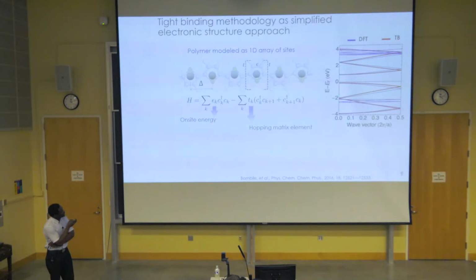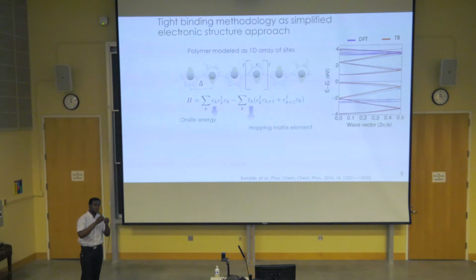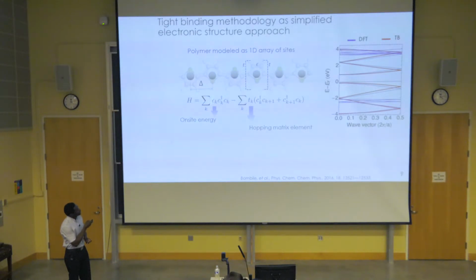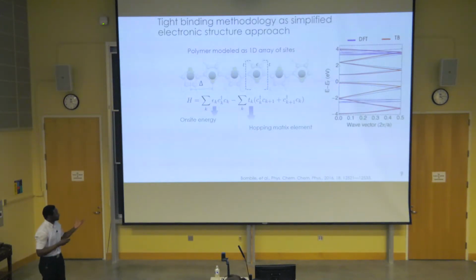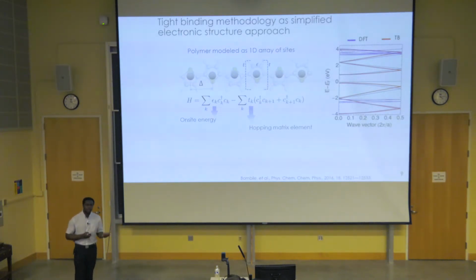And the energy of a charge carrier within this array can be captured by this tight binding Hamiltonian, where the first term here represents the energy of a charge carrier sitting on a single site. And the second term here captures how much the energy of the system is lowered when the charge carrier is able to spread out to the nearby site by quantum mechanical hopping. You don't need to know the details of the equation, but these are the creation and annihilation operators. But this equation has two parameters, the on-site energy and the hopping matrix elements. We parameterized this equation, determined these parameters, by reference to first principle calculations.